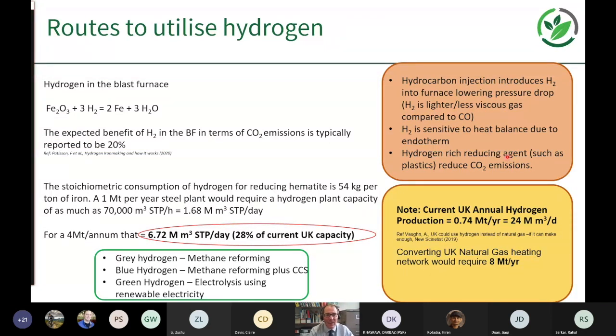So the hydrogen in the blast furnace reduces pressure drop in the blast furnace, which is beneficial because it's lighter and it's a less viscous gas compared to the carbon monoxide. The reduction of iron by hydrogen is endothermic, so it has a heat requirement. So it affects the heat balance, which limits the overall amount of hydrogen that you can put directly into a conventional blast furnace.